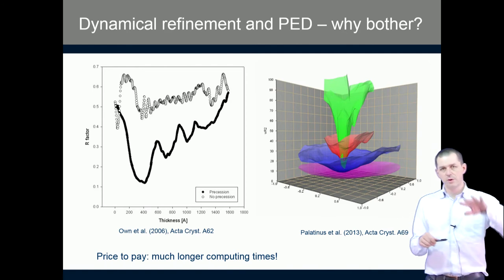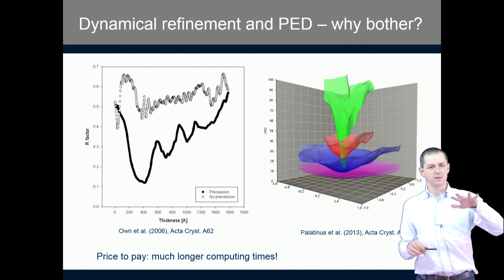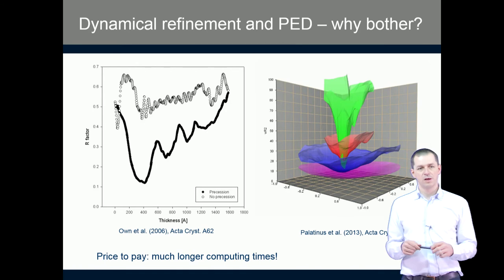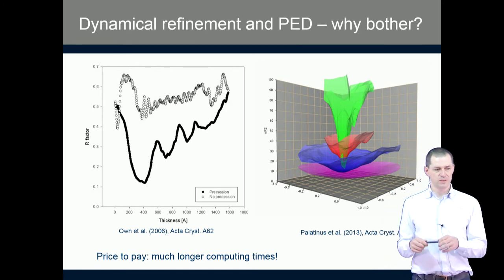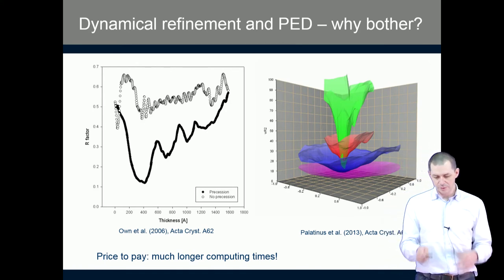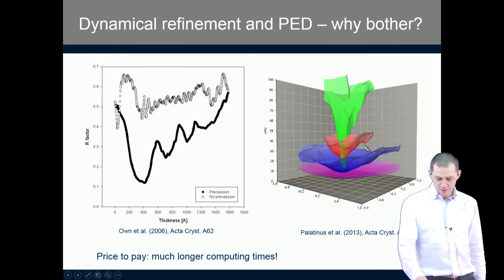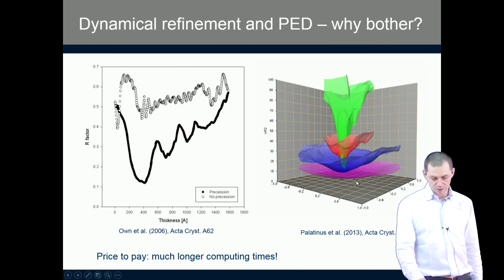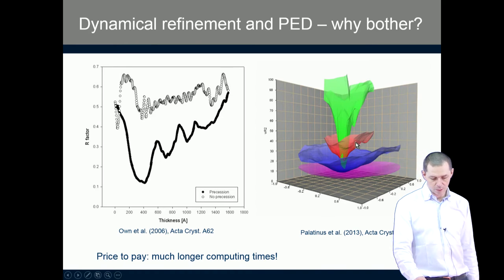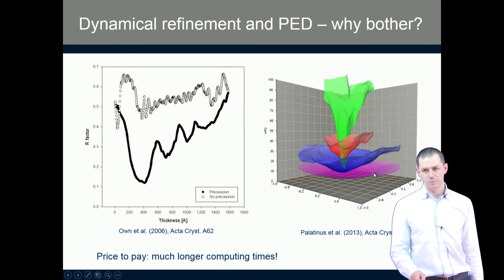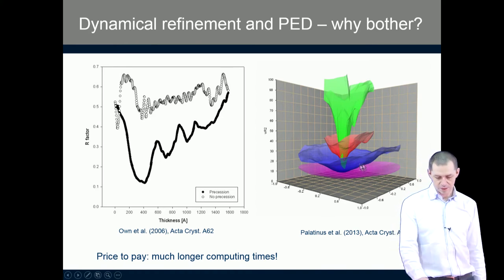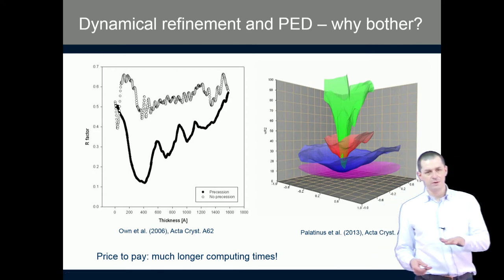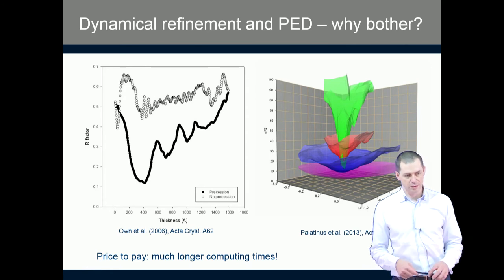The precession, because it is doing the integrating movement, integrates out a lot of this unwanted sensitivity, and the result are then plots which are shown here in the red, blue, and purple curves, which are the R values as a function of orientation for 1, 2, and 3 degrees of precession angle. You see that the curves are much flatter, and therefore it's much easier to find a good orientation and get a good match.